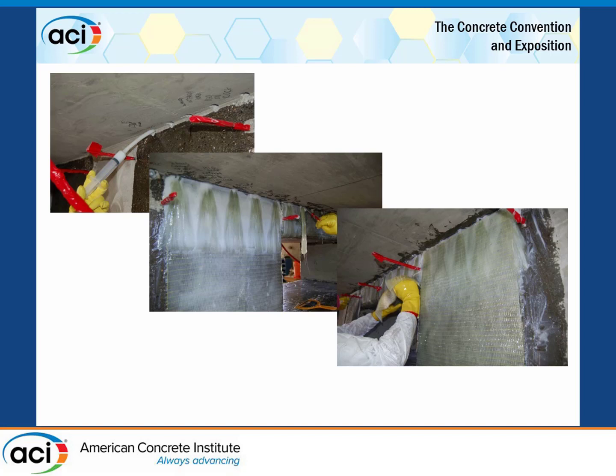I just want to show you how our anchors are installed. There's some differences in this concept, but again, the hole is drilled as high up as you can. We fill it half of the way with thickened epoxy. We take the pre-saturated anchor here, push it into the hole, fan it out, take that same thickened epoxy, butter it up, is what I like to say, and then take a second layer and sandwich it. So the anchor is actually between the two layers of glass there.